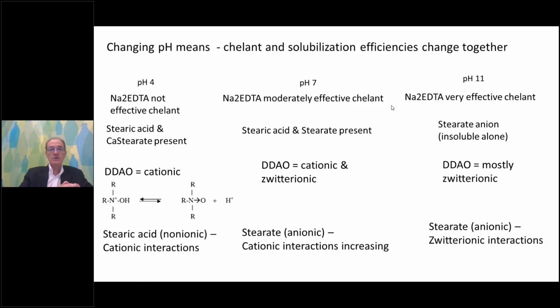Well, we can rationalize what's going on there because we have an effect of the surfactant, and of course we have an effect of the chelant at pH, low pH, say 4. EDTA salts are not very good chelants for the calcium, right? So what we have present is stearic acid and a lot of calcium stearate, and the cationic amine oxide is interacting with that. As we move up to pH 7, now our EDTA salts become better chelants, we generate more stearate, and we have stearic acid present as well, interacting with a cationic and zwitterionic form of the amine oxide.